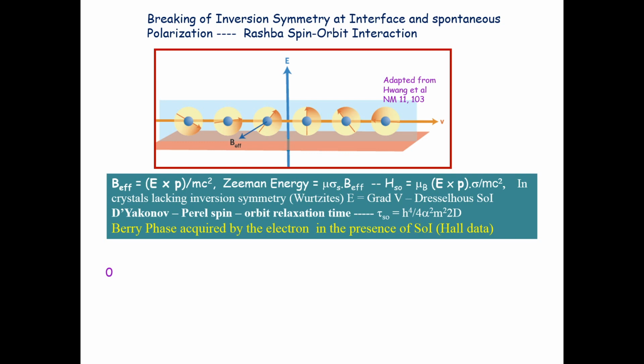But if the electrons are very close to the nucleus, the wave function gets distorted, and because of that you can have non-linear terms also here, cubic terms or higher order terms, odd in power. You see similar effects in crystals where there is a lack of inversion symmetry, like wurtzites, where the electric field is given as the gradient of the potential, and this is what is called the Dresselhaus spin orbit interaction. But this is different from Rashba, which comes essentially because of the interface.